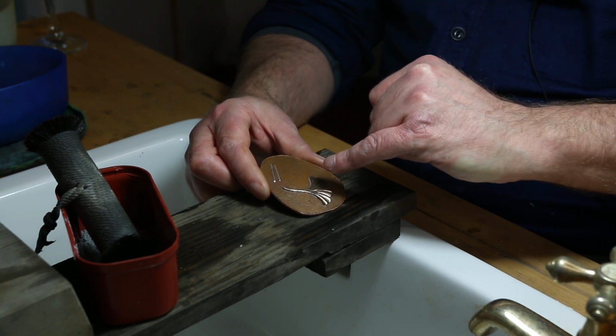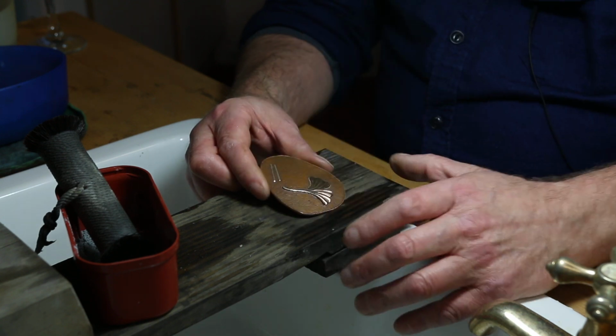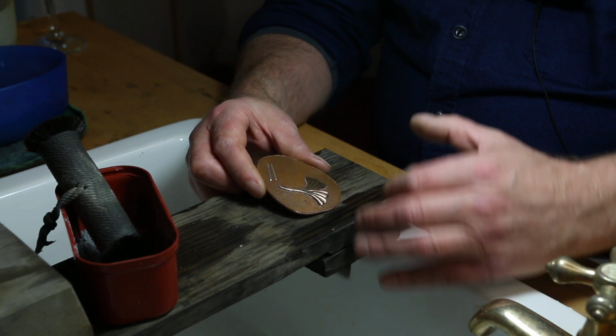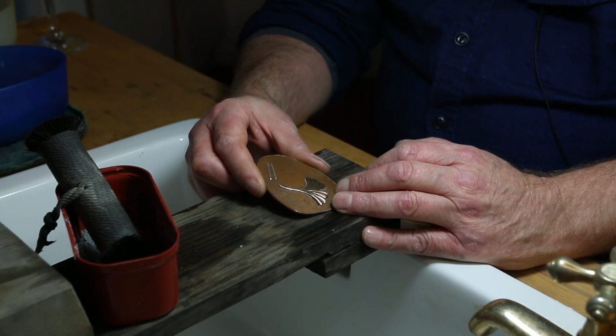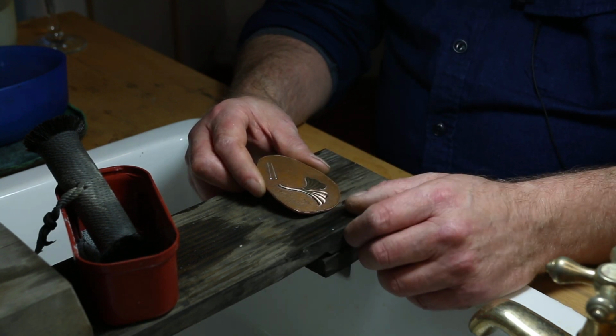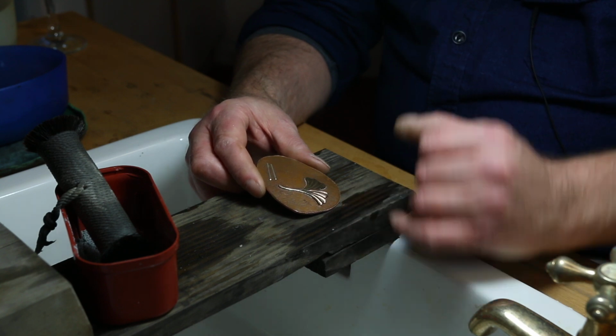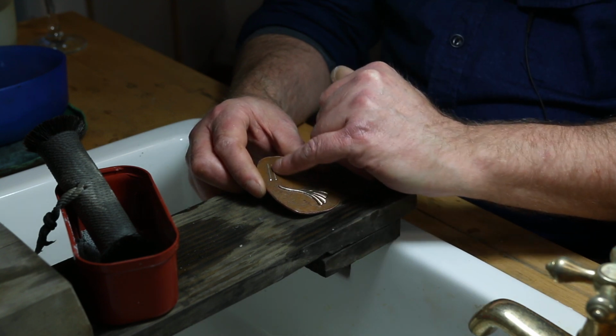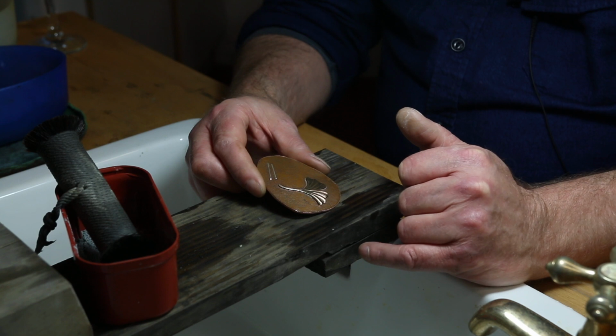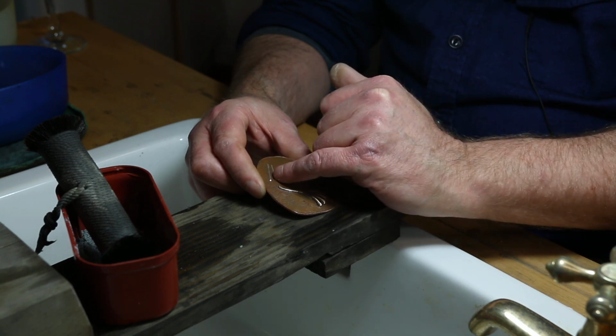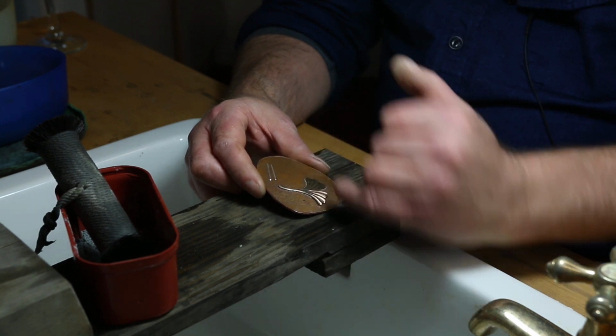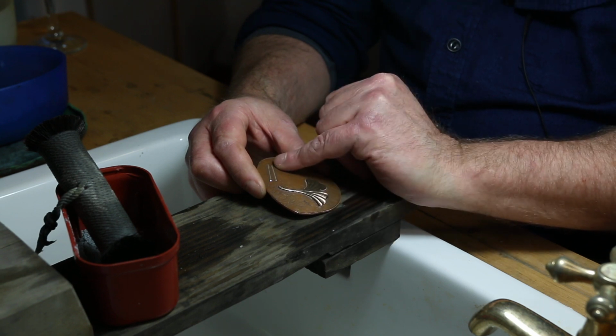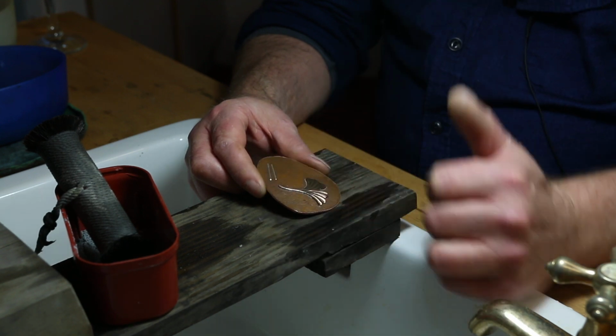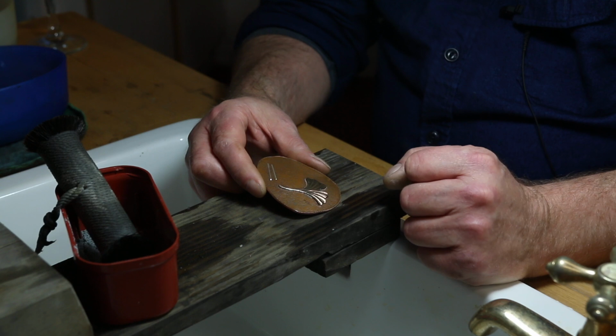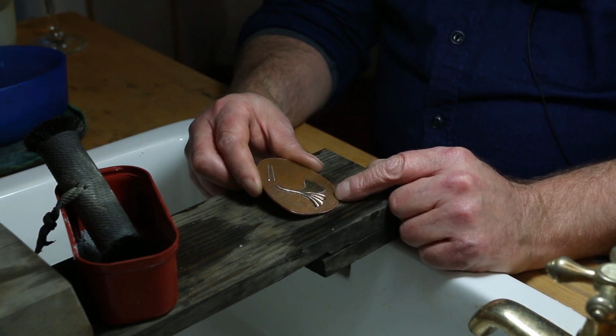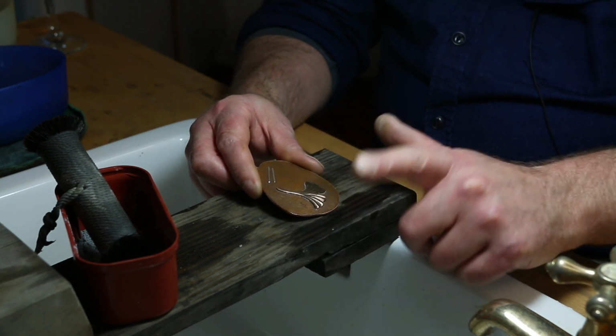Right, so in these copper salt type patinations, there's often a tendency for chlorides, because there are salts of various types in the mixtures. Those chlorides combine with the silver and create a silver chloride layer on silver, and that causes a yellowish film. If you see the yellow film on silver, because silver is white and you can see it easily, it also means that that film is on your copper and it's on your Shibuichi and everything.